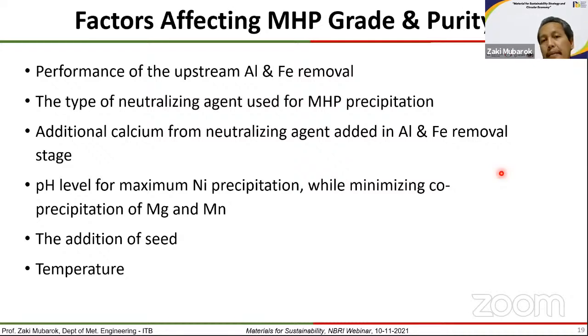And the factors affecting MHP grade and purity are quite important, because the purity of MHP will determine also the purity of the final product of nickel sulfate. One is the performance of the upstream aluminum and iron removal, as already shown in the flow sheet, that prior to MHP precipitation, the process is iron and aluminum removal in 2 stages. Another is the type of neutralizing agent used for MHP precipitation. If you use magnesium oxide, then you will have some addition of magnesium in MHP. If you use sodium hydroxide, then the sodium tends also to be contained in the MHP precipitate. So additional calcium from the neutralizing agent added in aluminum and iron removal can also be present there.